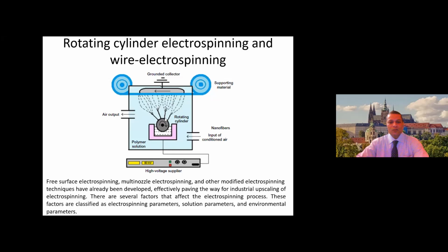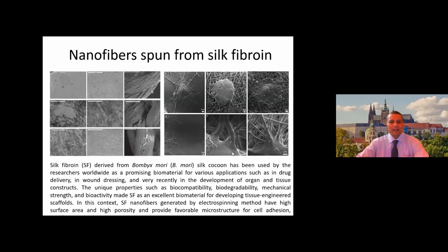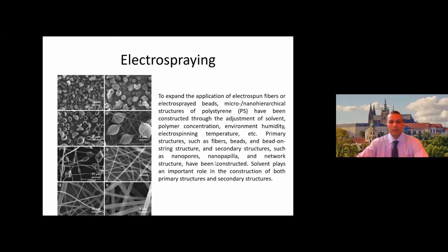So a film comes to the surface of this cylinder, and from the surface, several so-called Taylor cones are generated, which are split into fibers, and we are able to cover any surface of fabric, already existing fabric or yarn or paper, with a mat or membrane of nanofibrous material. Nanofibers can be produced from natural polymers, especially some researchers try to produce nanofibers from silk fibroin and from cellulose, and they are biodegradable. They are less polluting.